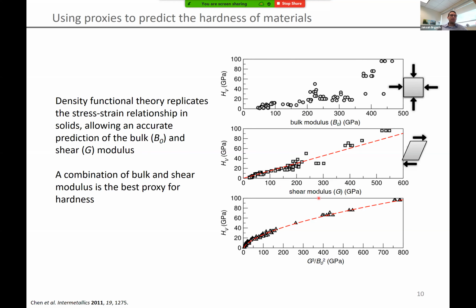If you plot a material's shear modulus, that's going to be resistance to lateral strain across the crystal structure, you can see that there is, in fact, a better relationship. It sort of starts to fall apart at really high Vickers hardnesses and high shear moduli. Nonetheless, there's a fairly nice linear relationship here.